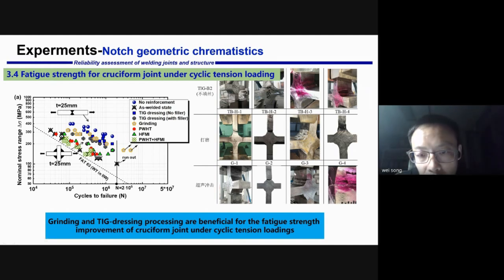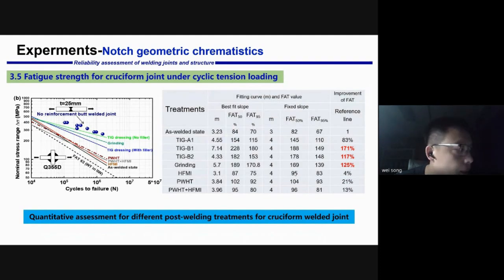But it should be noted that for the HFMI treatment, it failed from the point of HFMI treatment. So we can summarize the result for the cruciform welded joint. We can see that TIG dressing and grinding, no matter with or without filler, will be the best way to improve the fatigue strength for the cruciform welded joint.